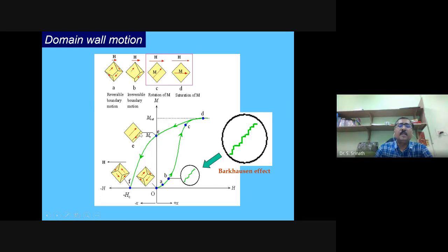There is only a small nucleation of domains, and a small portion of magnetization is switched, but not the entire thing. There is a large portion of magnetization pointing along the field direction because of the coupling between the spins. Thereby, there is a finite magnetization present even when the field is 0, and this magnetization is called remanence magnetization or remnant magnetization.